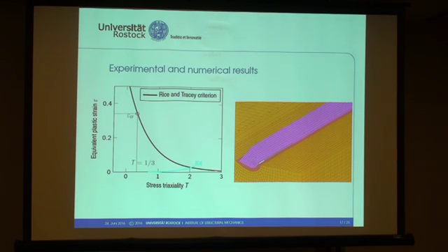And here I plotted the plastic strain as a function of the stress triaxiality of the first element, which gets deleted here, the location of crack initiation, and also the function of the Rice-Tracey failure criterion. You see that the stress triaxiality at failure is 2.1 or 2, and the plastic strain is around 5%. And I did that for the finite element analysis of all 4 experiments. Those are the paths of the location of crack initiation of all 4.